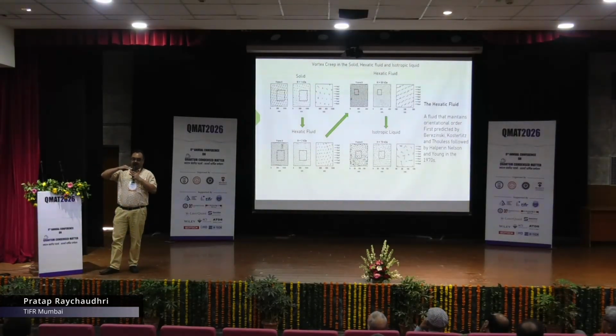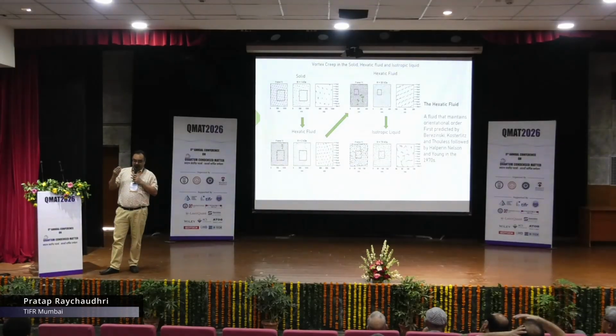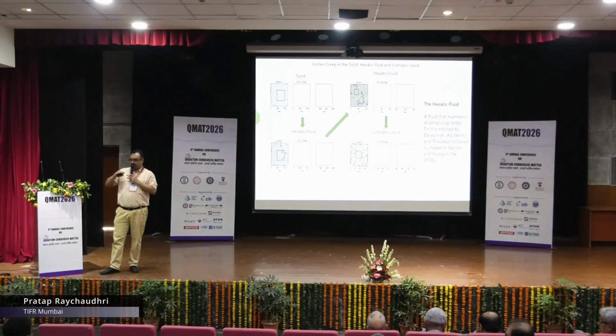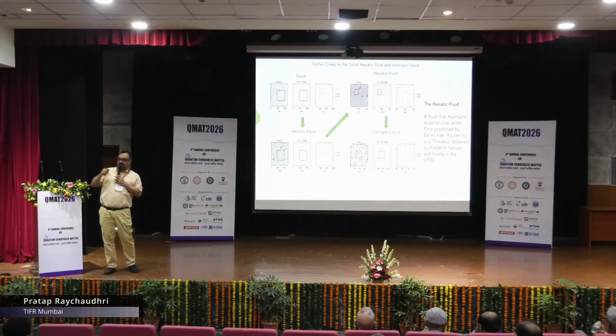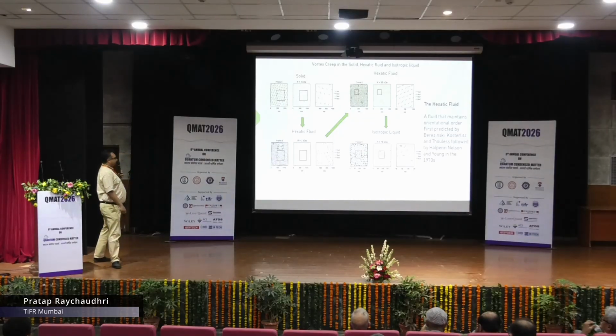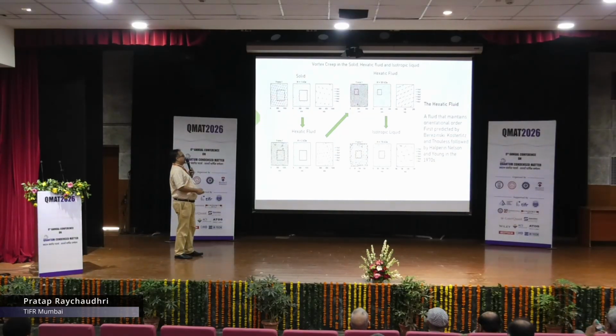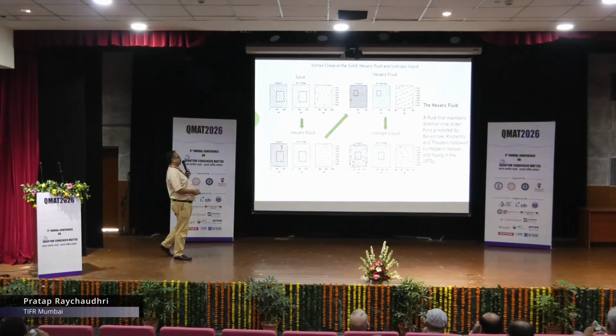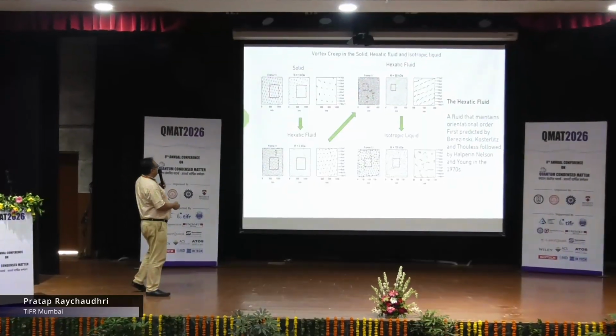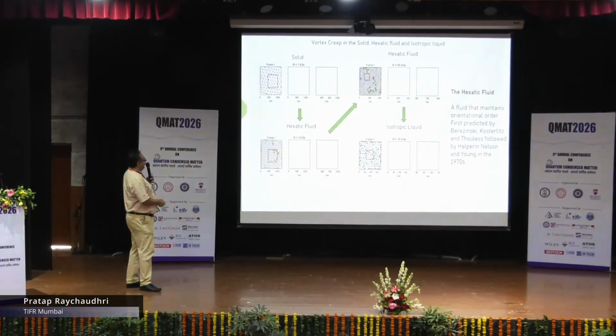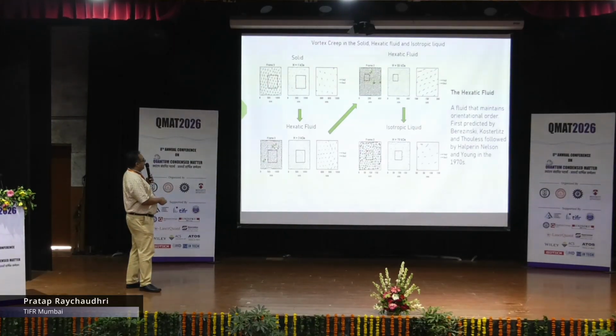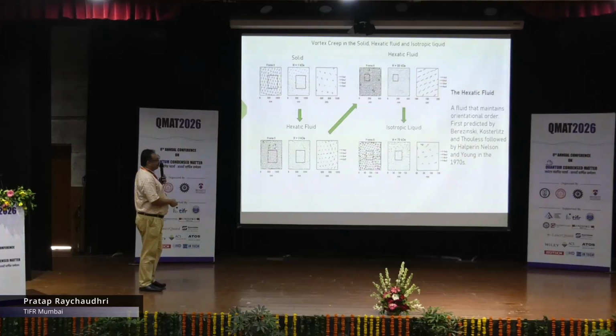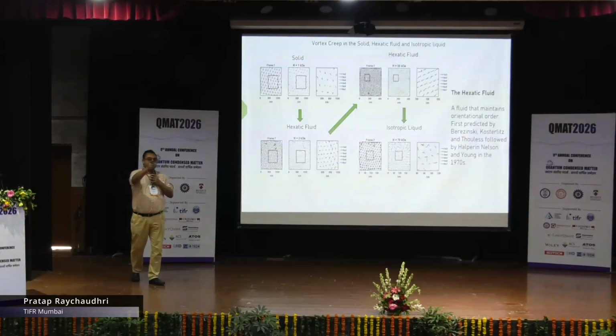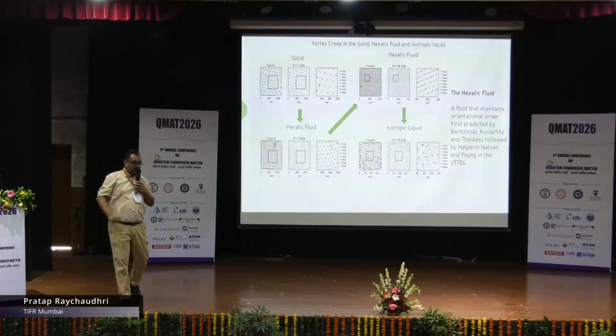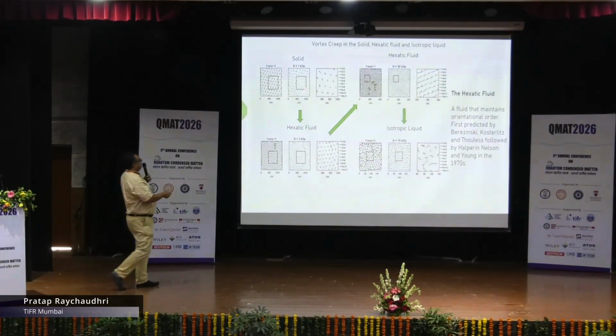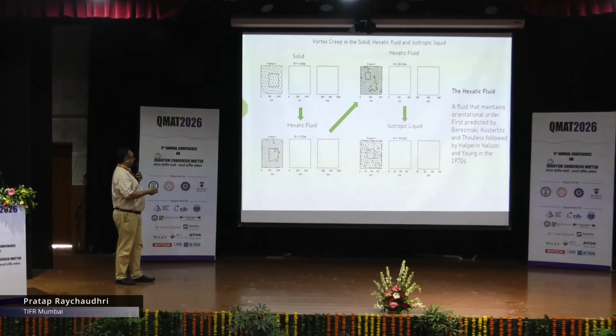Now, when you have reduced the thickness of the superconductor, you have not just increased thermal fluctuations, but you have also done another thing. You have created a two-dimensional vortex lattice. So now the vortex lattice is consisting of point objects. And it was shown way back in the 70s, following the work of Berezinskii, Kosterlitz, Thouless, but it was primarily shown by David Nelson, that you can have a two-step melting here, where you have a state which is called a hexatic fluid in between a solid and a liquid. It can flow, but it flows preferentially along certain direction because it maintains orientational order, though positional order is destroyed. And this was the first realization of hexatic fluid in any vortex system.